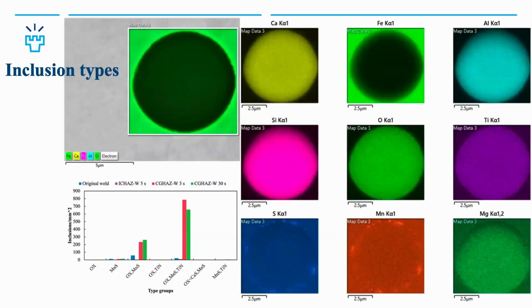And when we see the chemical composition of these inclusions, this example is from the original weld, and it can be seen that it is a mixed oxide, but on the surface there is manganese sulfide, a little manganese and a little sulfur. And when we look at the distribution in all cases, we see that in the coarse-grained heat affected zone where we had many more small inclusions, they have this manganese sulfide particle, and it may be one explanation, because in the coarse-grained heat affected zone simulation, we go to a peak temperature of 1350, and at that temperature manganese sulfide nucleation can already happen.